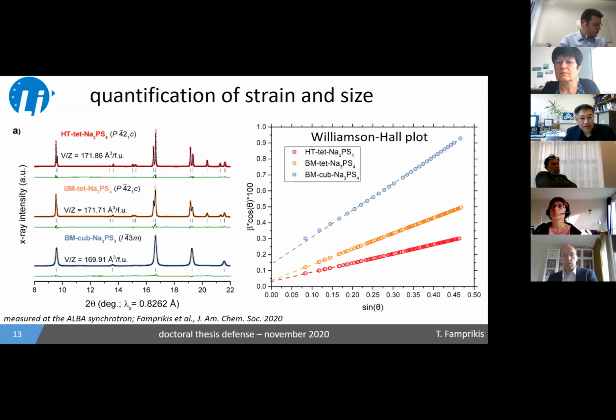If you're not very familiar, don't worry too much. I will explain what you need to get out of this. Basically, we're plotting the variation of the width in a very particular sense as a function of the diffraction angle theta. Basically, what you get from this is that the crystallite size is proportional to the inverse of the intercept in this plot. So you can see that we have a very similar crystallite size for the two tetragonal samples, but a much lower crystallite size for the ball mill sample. So in the hundreds of nanometers for the tetragonal samples and down to about 25 nanometers for the ball mill one. And the gradient here is actually proportional to the microstrain.